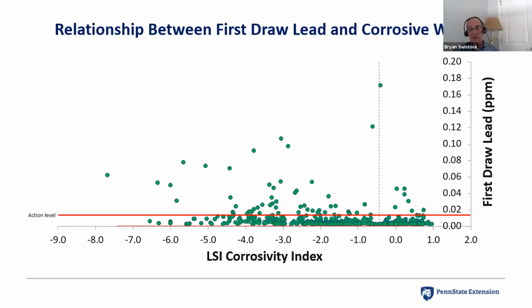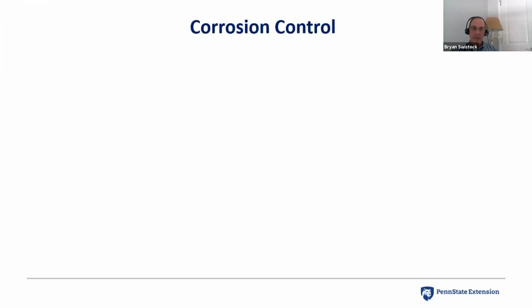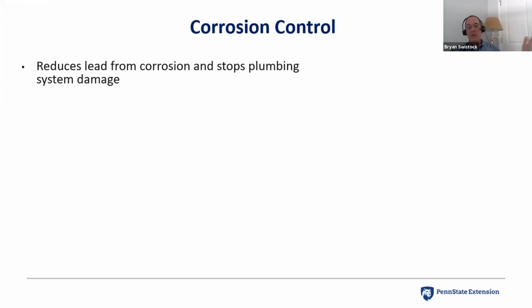In those cases, we often have to look at things like the chloride sulfate mass ratio, to see if we have galvanic corrosion occurring in the absence of a calcium carbonate problem. So there are all sorts of little intricate details, and you often have to deal with lead problems case by case because there are so many complexities to it. But as a generalization, we can definitely say that corrosion is the problem. So how do we do this? How do we treat corrosion?